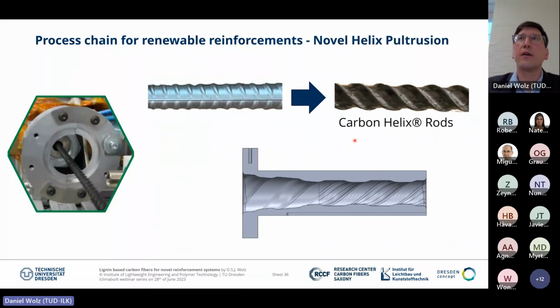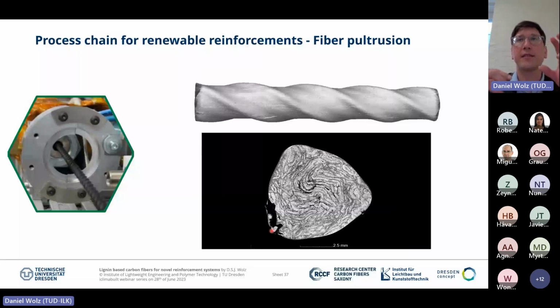So this mechanical pultrusion is needed because, if you look at steel rods, you see that there are bulges for enhancing the mechanical stability. This has also been done in the invented carbon helix rods by the pultrusion process itself. Here you can see the nozzle where the pultrusion is done in situ within the process, by pultrusion of the carbon fiber polymer rod. If we look into this rod, this is a computer